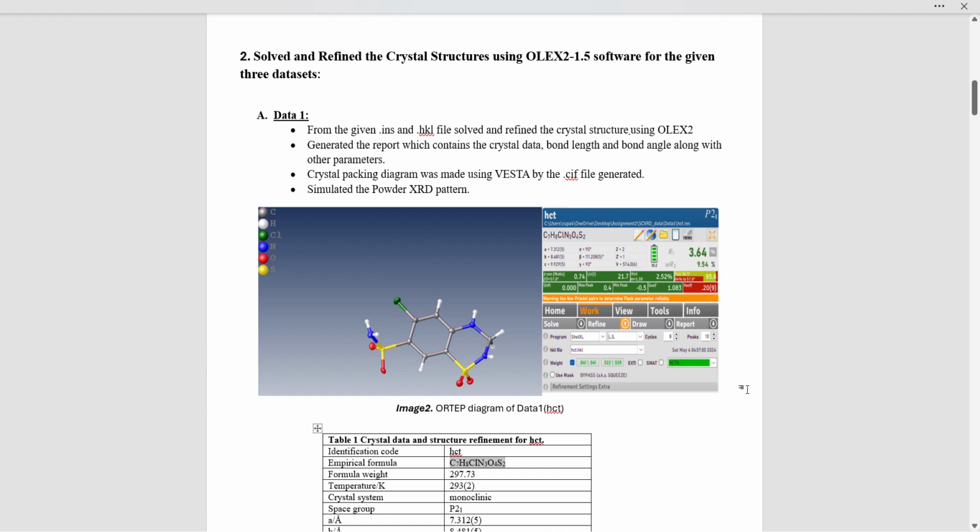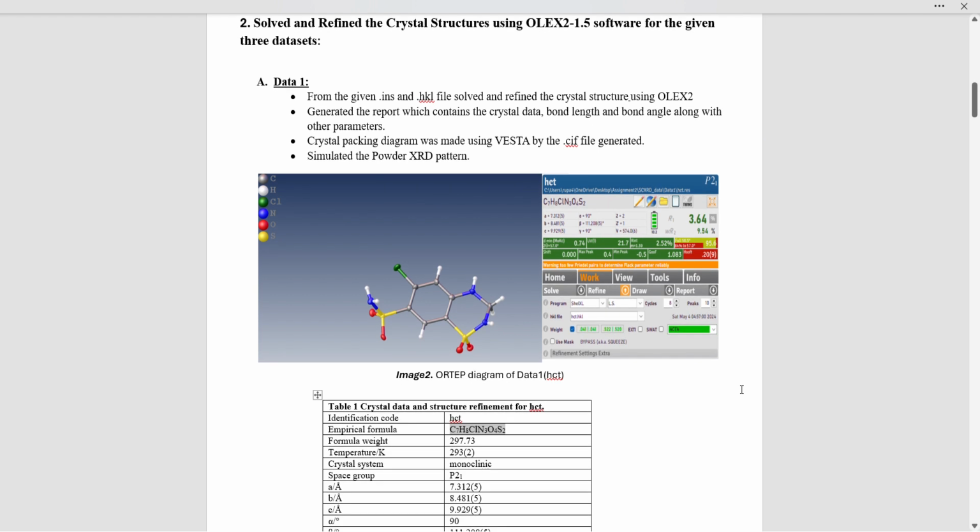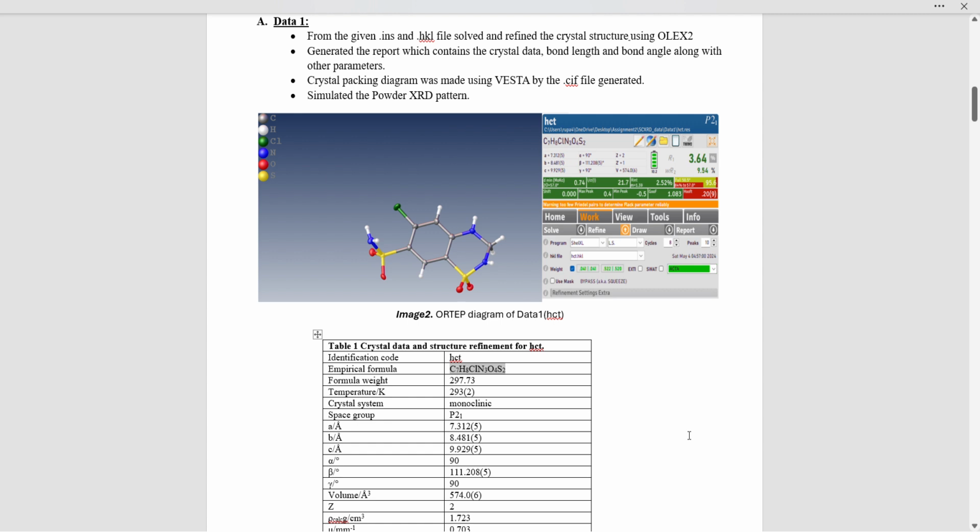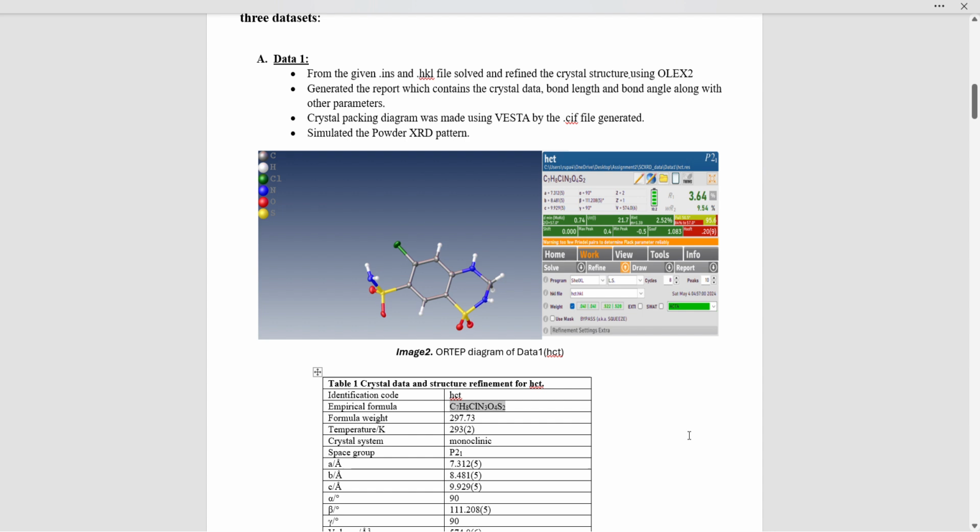Then I assigned the atoms according to the provided model structures and refined it. After the first refinement, I refined it again anisotropically and I observed a very significant decrease in the R value. After that I added hydrogen and refined it again. After doing three to four refinements, when I get a considerably low R value, I also include the weight parameter and refine it again. And I refine it until I get a shift value of 0.00. At the end of this refinement, we also get a corrected chemical formula of the compound.